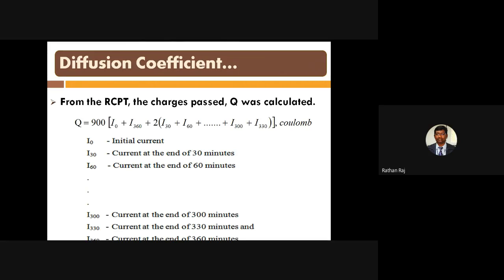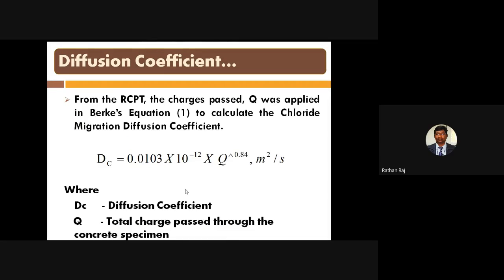After substituting all these values, I0 is the initial current, the current at the start. Then at every 30 minute interval, I30, I60, I90 and so on, up to 360, the current was measured. After substituting in this relation, we get the charge passed value, the Q value. The diffusion coefficient value is then calculated using Berke's equation. After substituting the Q value in this equation, we get the diffusion coefficient.